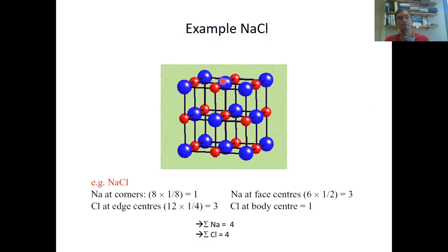Okay, therefore with face-centeredness, we also have an atom here in the body center. But you see that this atom is different from the atoms that sit here on the corners. Therefore, translational symmetry from the corner to the body center does not hold. Therefore we have no body centeredness. Of course, we cannot have face-centeredness and body-centeredness at the same time. It can only be one of the two. In this case, it's face-centeredness.